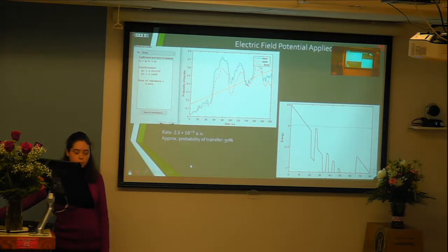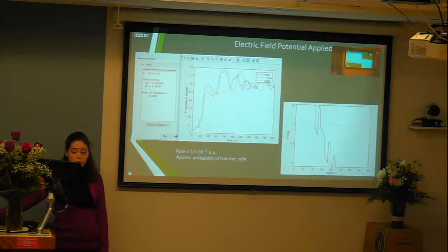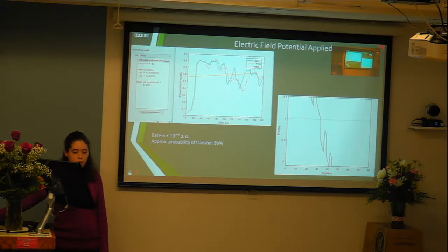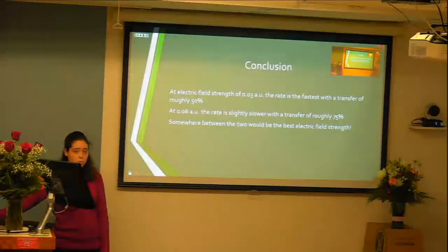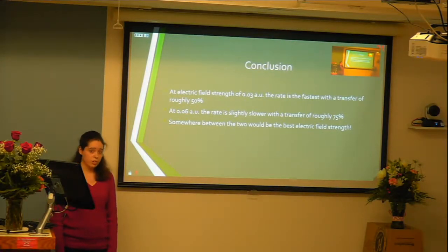And increasing it to 0.03 AU, the rate increases and so does the transfer. Increasing it to 0.06, the rate decreased a little bit, but the transfer still increased. And at 0.09, the rate is its slowest, but the probability of transfer is at 80%. So in conclusion, at an electric field strength of 0.03 AU, the rate is the fastest with a transfer of roughly 50%. And at 0.06, the rate is slightly slower with a transfer of roughly 75%.